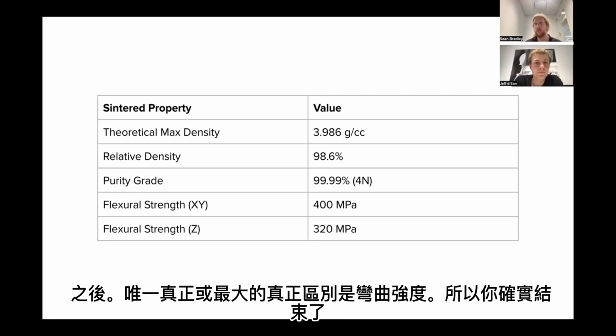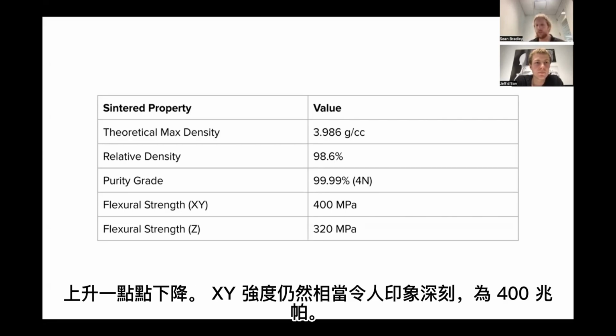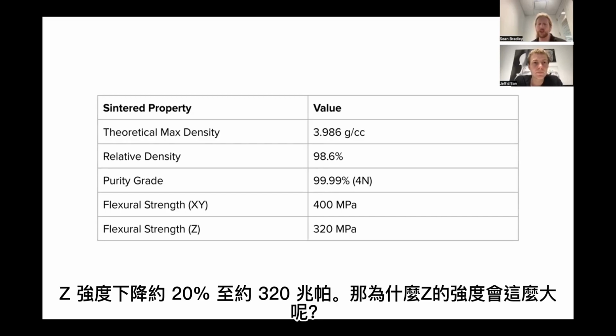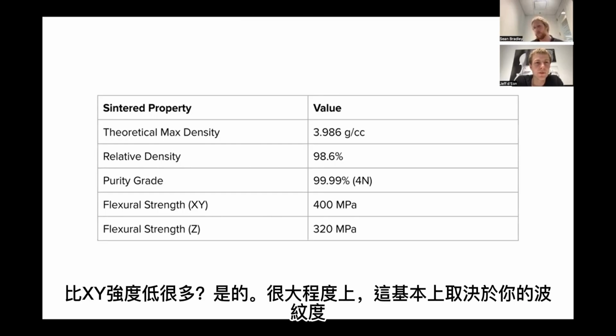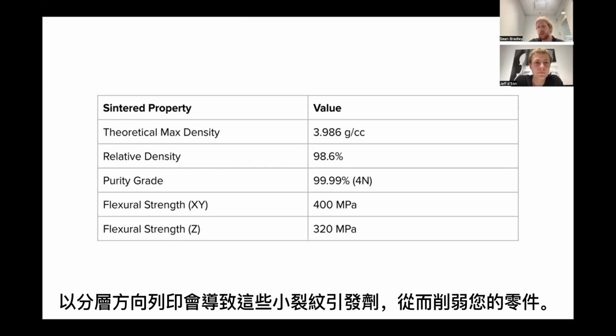The only real, the biggest real difference is the flex strength. So you do end up going down a little bit. The XY strength is still a pretty impressive 400 megapascals. The Z strength drops by about 20% to about 320 megapascals. So why would the Z strength be so much lower than the XY strength? Yeah, so largely that comes down to basically the waviness as you're printing in a layer-wise direction will cause these little crack initiators that can weaken your part.